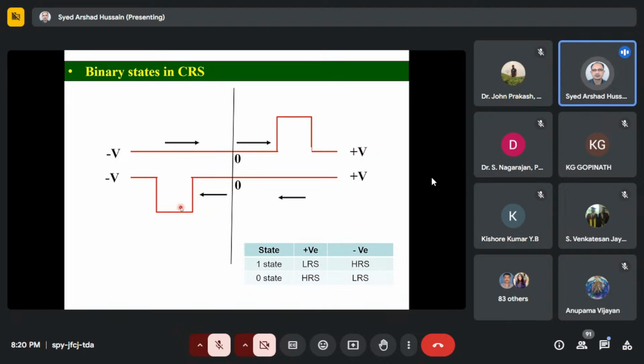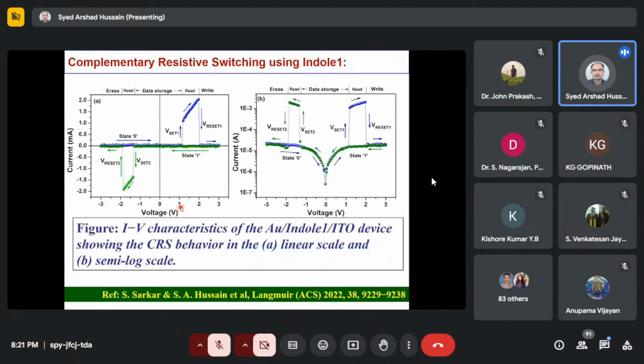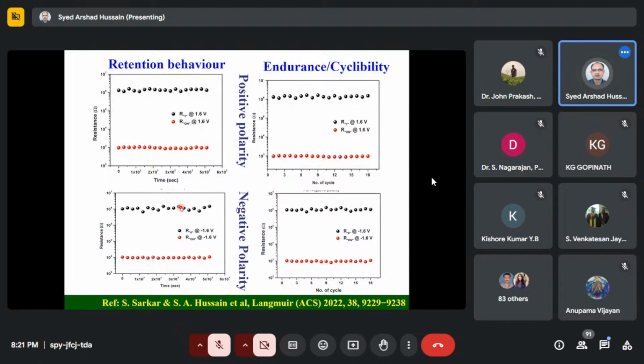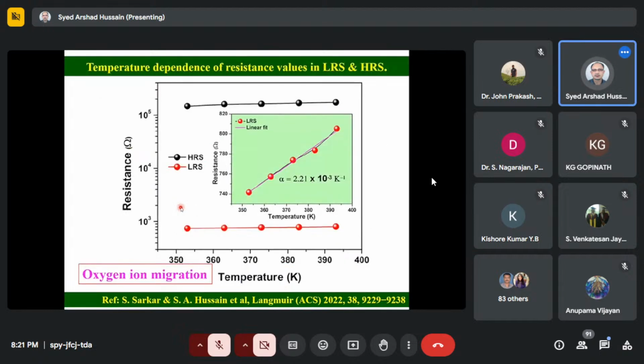So we have seen that this same indole derivative, when treated up to a certain heat or temperature, has its switching behavior change from bipolar to CRS. Okay, so we again characterized the retention behavior, stability, endurance, cyclability, everything, and we found that it shows very good stability. And here mainly we have seen from the fitting characteristics that oxygen vacancy contributes to the conduction channel across the two electrodes.